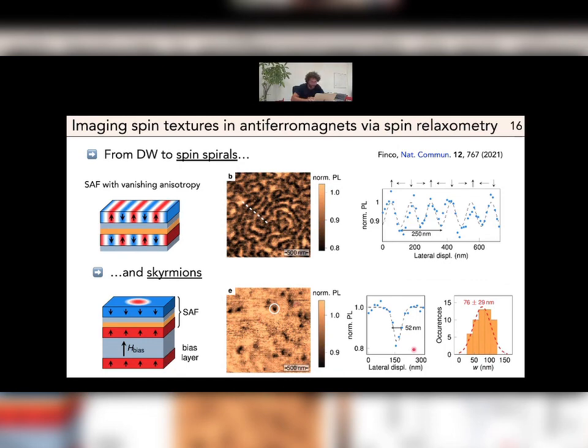By just taking line cuts, we can see a distribution of the size of the skyrmions that is around 80 nanometers, and we believe that this is essentially limited by the distance between our NV defect and the sample. So here, essentially, what we have done is to introduce a new way to measure spin textures in antiferromagnets that relies on measurement of magnetic noise rather than a static magnetic field. That might be useful for studying antiferromagnetic materials that are perfectly compensated and will not produce stray magnetic fields.